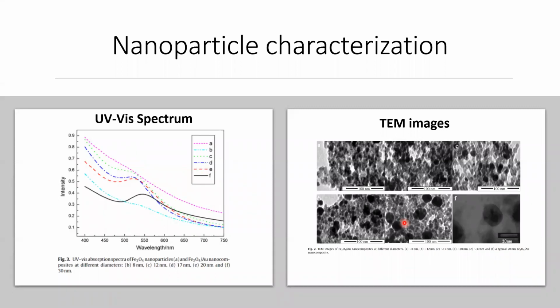Now let's talk about the results. The results basically start with the nanoparticle characterization. On the left side, we see the UV spectrum of all the nanoparticles. The pink line represents the magnetic nanoparticles, and the other curves represent the core shell structures with different diameters ranging from 8 nanometers to 30 nanometers. And on the right side, we see the same nanoparticles, but with the transmission electron microscopy images, where we can see the morphology of these nanoparticles and their dimensions.